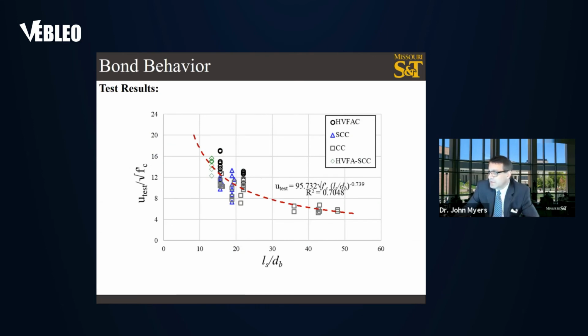When plotted here, you can see the curve fit that was developed for these series of tests, as well as a database that we have at Missouri S&T on conventional concrete. And you can see they all generally follow the same empirical relationship for bond.